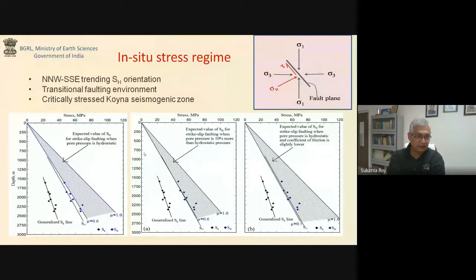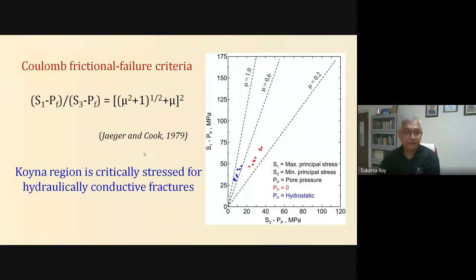Now, when we plotted the minimum horizontal stress, the maximum horizontal stress, and the SV, you can see on the left panel here that the SV and SH max are very close to each other. So we did a small calculation where we tried to increase the pore pressure by about 10% above the hydrostatic, and in another case, we reduced the coefficient of friction by about 5%. And in both cases, we see that the faulting regime can change very easily from strike slip to normal and vice versa. You can see the SV and SH max. In one case, SH max becomes smaller than SV. In the other case, it becomes higher than SV. So these are some of the interesting things that we found from the stress regime.